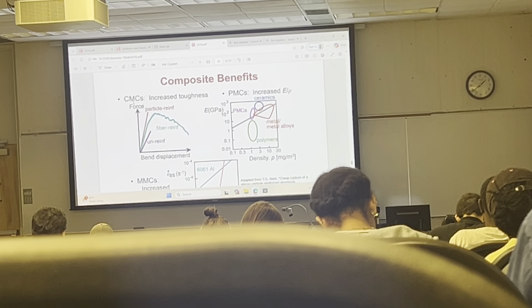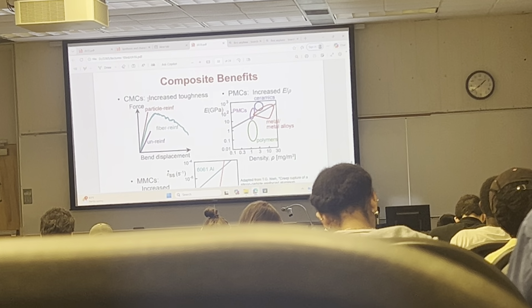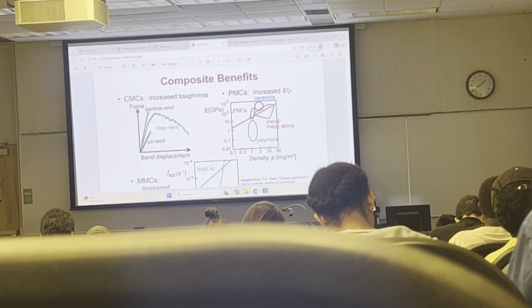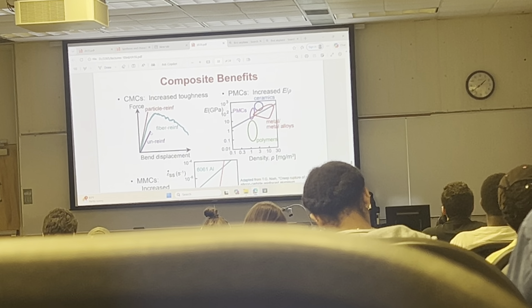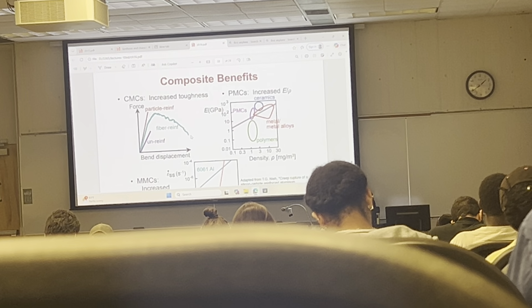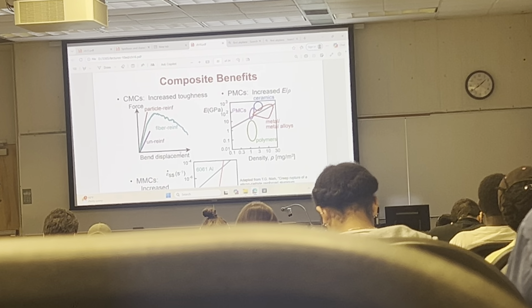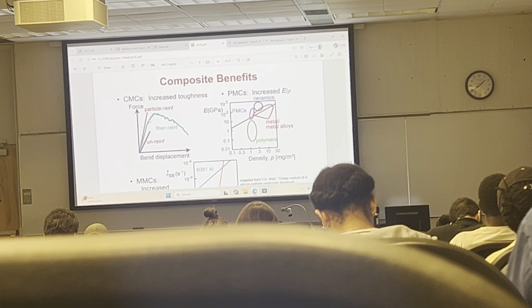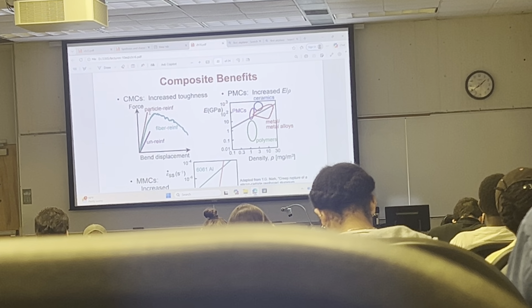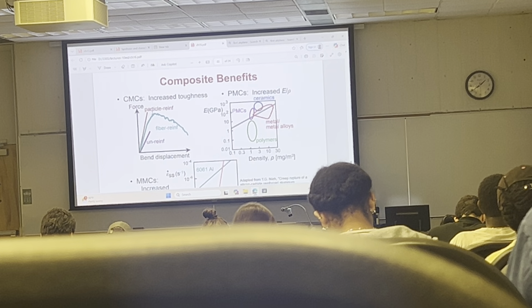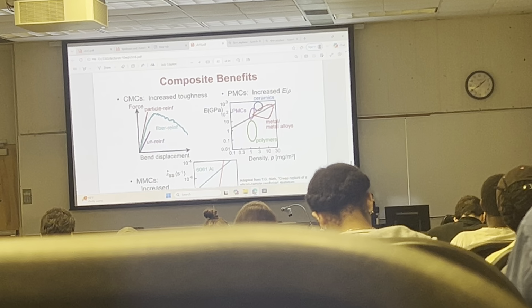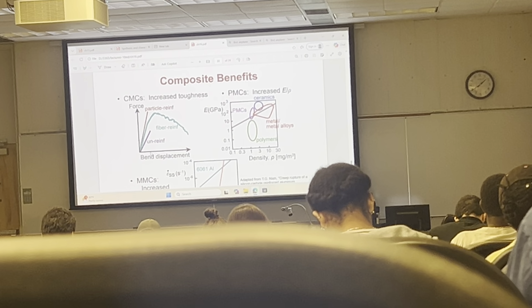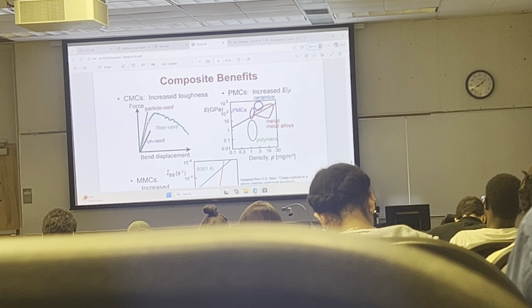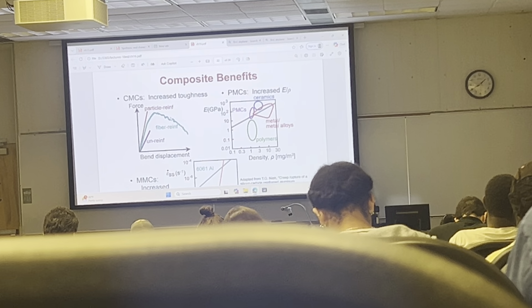Composite benefits. Ceramic matrix composites. This is particle reinforced, this is unreinforced, and this is fiber reinforced. Force versus bending displacement. What do you see here based on the data? If you just simply add particles that are spread, you can increase the modulus. So the stiffness is higher here, but the strain, or here in terms of the bending displacement, these materials are brittle. You add the fiber, you take it to the higher level of strain before it completely fractures.